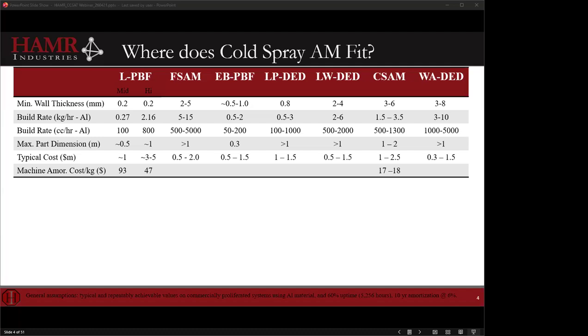Likewise, build rates. We can have build rates that are as low as tens or 100 cc's per hour, or a few hundred grams per hour, and we can have build rates that are as high as several kg to tens of kg per hour, for some of the solid state methods and the wire based methods. Likewise, part dimensions. So cold spray fits within this. It tends to favor the high build rates, the large part sizes. It doesn't have a lot of resolution. So it's in a space that's somewhere close to a laser wire or a wire arc DED. And then the system cost also kind of fits similarly in that space, a little bit less than the really large powder bed fusion systems or e-beam systems, more comparable to something like a typical wire arc cell.